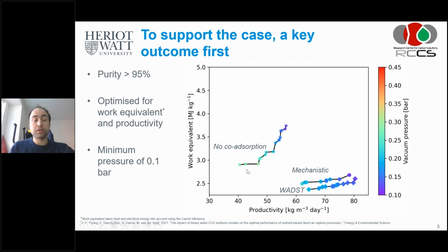They are basically Pareto fronts for CO2 that is captured and purified to purity over 95%, and optimized for work equivalent and productivity. And what you see immediately is that if you don't have a co-adsorption description in your model, and that's the Pareto front that you see here, then the predicted work equivalent is higher and the predicted productivity is lower than when you do have co-adsorption descriptions. So here immediately you see why it is important to have a very good understanding and also mathematical description of water CO2 co-adsorption.